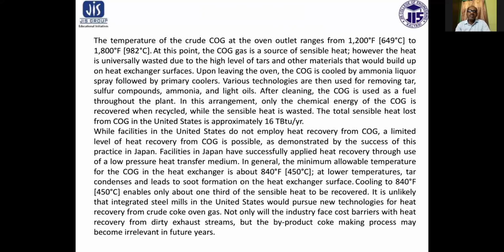However, the heat is universally wasted due to the high level of tars and other materials that would build up on heat exchanger surfaces. Upon leaving the oven, these gases are cooled by an ammonia liquor spray followed by a primary cooler. Various technologies are then used for removing tars, sulfur compounds, ammonia, and light oils. After cleaning, this coke oven gas is used as a fuel throughout the plant. In this arrangement, only the chemical energy of the COG is recovered when recycled, while the sensible heat is wasted. The total sensible heat lost from COG in the United States is approximately 16 TBtu per year.